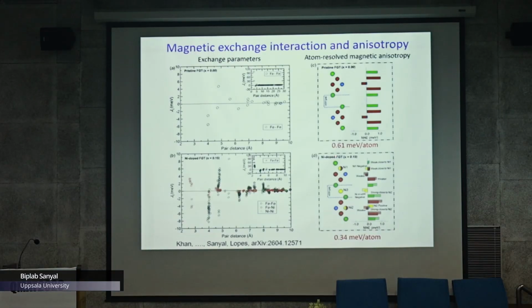But when we dope with nickel, you see a lot of things happening. First of all, this magnetic anisotropy, which was out of plane, becomes weaker. And also the atoms in the van der Waals plane show the opposite direction of magnetic anisotropy. So if you sum them up, the total magnetic anisotropy, which is still perpendicular, is decreased significantly compared to the pristine system. So basically, I said that there were two things: one is the suppression of the Curie temperature, and the second is the suppression of the perpendicular magnetic anisotropy. Both of them we could show by nickel doping.